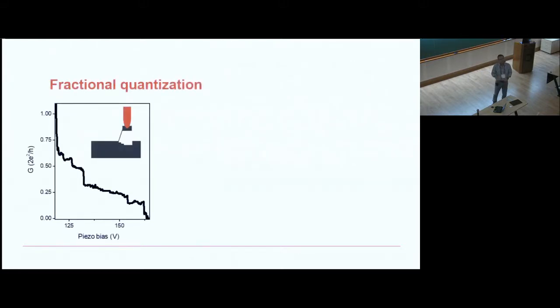What happens if I continue to exfoliate or pull out graphene in a discrete manner, atom by atom? Will I have an effect of that in the experiment? It turns out to be yes. And suppose I do it extremely slowly. This is a very difficult experiment. If I go to one flake, one bridge, which is connecting the graphite and the tip, and I do it very carefully, then I see the conductances are quantized not just at one and then drops directly, but it shows a series of features at very low conductances.